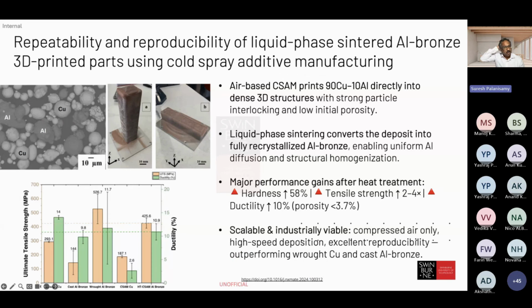And aluminum bronze material, as I said, aluminum and copper, again using a different sintering process, 90% copper, 10% aluminum, into direct metal 3D structure. You can see how the performance looks, using different conditions: cast aluminum bronze, wrought aluminum bronze, and cold spray aluminum bronze, compared with the heat treated aluminum bronze.